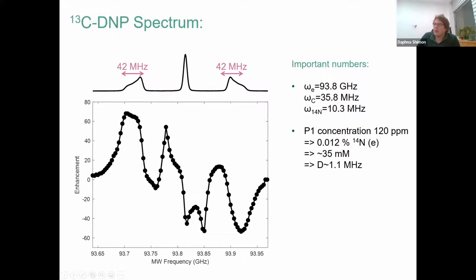We're working at 94 gigahertz for the electron, which is about 36 megahertz for the carbon. The width of the two outer EPR lines is about 42 megahertz, so that's basically wide enough to show a cross effect there. And the average dipolar interaction at 120 ppm is about 1 megahertz, so that also seems to match. And I'll discuss more about finding DNP within a single crystallite, but that will come towards the end.